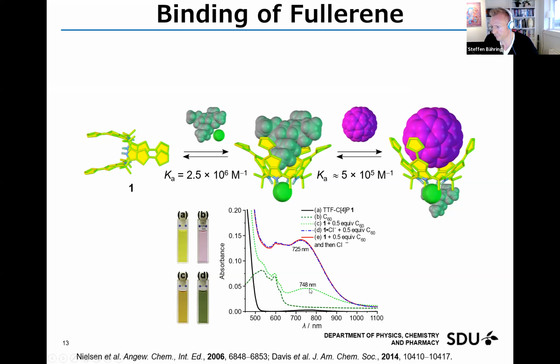But if we introduce tetrabutylammonium chloride to this solution, then the CT band is increased quite dramatically because this induces the cone conformation, and the complexation is much more pronounced with the fullerene. These cartoons are of course based on crystal structures, so it clearly shows that the fullerene is situated within the cavity of the TTFs.